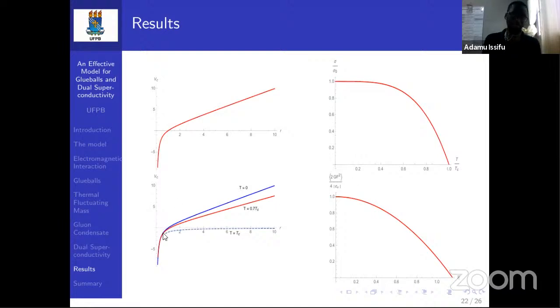And then here is the Cornell potential as a function of temperature. So we realize that at zero temperature, we have this. We have strong confinement. And as the temperature increases, the gradient of the graph decreases, showing that confinement is reducing. And at the critical temperature, you see, we have a thermal hadronization at that point.